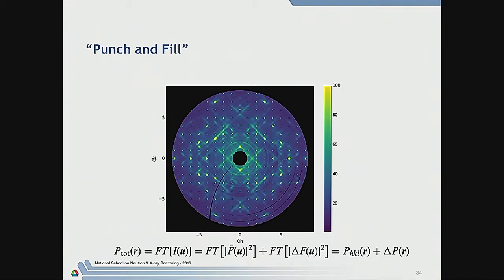All you know are all of the possible interatomic vectors from any particular site. So if a site has atom A, then you'll find all of the types of interatomic vectors that connect A to the other atoms in the crystal. And also, if there's atom B, then you'll also be summing that with all the sites that surround atom B. So it could be a very complex function. But you don't know, for instance, if there is an atom at this position, how it correlates with the one that may be at a slightly different position. You just have the distribution of those vectors.